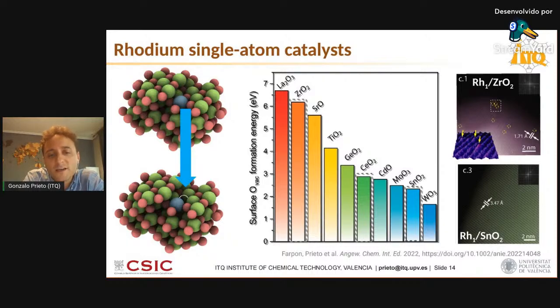So we decided to take a look at how energetically easy or difficult it is to create surface oxygen vacancies on different oxides so that we could make a selection of target support materials for our catalyst. And this is what I'm showing here on this plot in the center of the slide. I'm ordering a number of different oxides in terms of how easy it is to generate oxygen vacancies on their surface. So this is essentially the oxygen vacancy formation energy. And we decided to concentrate on three examples that span the whole range of energies. So from tin oxide, quite on the right-hand side, so quite easy to generate oxygen vacancies, all the way to zirconia on the left-hand side of the plot. So a very difficult to reduce oxide, very difficult to generate oxygen vacancies in that oxide. And ceria, which is an oxide of intermediate behavior. And we prepared rhodium-based single atom catalysts on those three supports to start with.